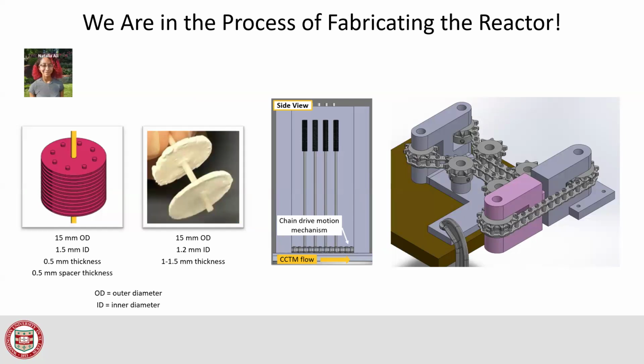What's really cool about working with engineers, I'm a chemist myself, so I just think about the atoms and the molecules. But they think about, well, actually, how do you get this into a process that will work? You actually have to take the material and turn it into something that's going to be in the reactor. So for us, we have a reactor. And the way that they wanted to do this was to create a bunch of little discs and put these discs on a line. And why that's good is because a disc is going to have high surface area. So there's going to be a lot of regions where oxygen could be exchanged with water, or it could leave the crystal. Basically, the more surface you have, the easier it's going to be for the oxygen to leave the crystal.